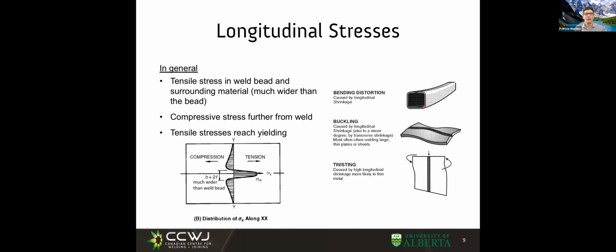For example, if you're welding thin sheet, and those of you who have welded probably have had this experience. If you're welding a thin sheet material and you make a weld that is somewhat thick, the weld and the area surrounding the weld want to shrink, but the rest of the material that was always cold doesn't want to shrink and ends up buckling, looking like this. And it's such a paradox because you start with a perfectly flat plate and you wonder what the hell happened. Some people think that when you overheat the plate it bends because the heat revealed some internal flaws. No, what happens is that the weld is pulling a lot of tension, and so these other sides are in compression, and if they are very thin, they are very easy to buckle.